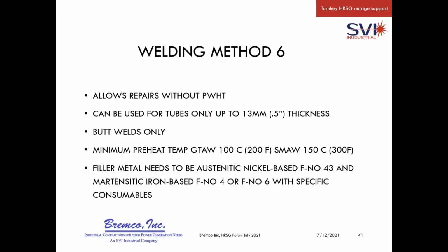We have done approximately 100, 120 welds with this weld method 6, and we've had one failure, I guess, that we had to cut out and perform in the traditional method. The beauty of weld method 6, obviously, is when you're down and you need power immediately, you have the ability, it'll minimize your downtime significantly. As you saw on the slide before, if you have to go 6 rows deep and that happens to be 3 headers, you'd have to do a post-weld heat treat on each one of those. And a post-weld heat treat is typically 14 hours per post-weld heat treat. So you're now talking 4 days just to get that out. Where with the weld method 6, you can probably get the whole project done in a day and a half to 2 days.